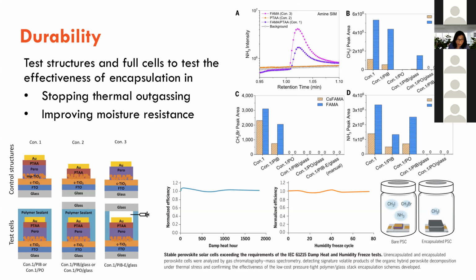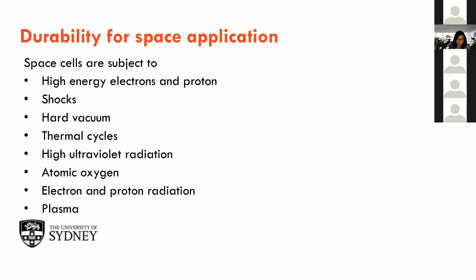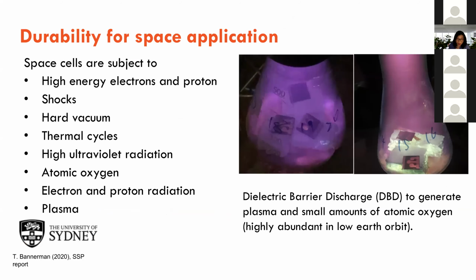With humidity freeze, we cycle them through -40 to +85 degrees at high humidity as well. So if you have any moisture being trapped into the cell, it will crystallize and break the joints of the cell. And we found that our methods work really well, and that we didn't have problems after long cycles of humidity freeze. So yeah, thermal cycles is doing well.